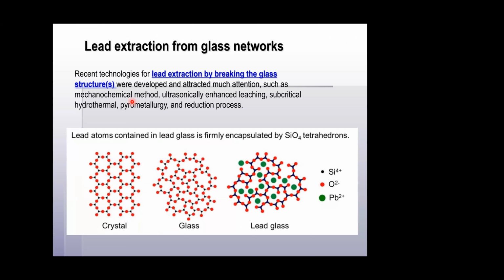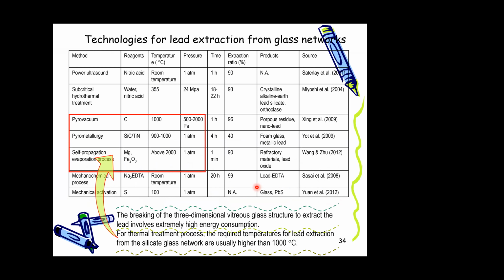But one fundamental problem in the scientific community is that the glass matrix that captures the lead is a very tight form, which means the lead ions are very difficult to extract. You pretty much have to destroy the glass network. One possible way is to melt, basically dissolve, the entire glass. You can imagine how much silicon oxide structure you have to destroy and dissolve. There will be a lot of acid and chemicals used. So a lot of people try different methods to extract the lead, if not also recover it.